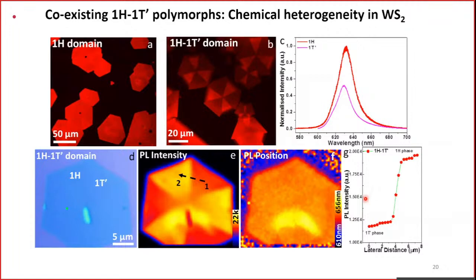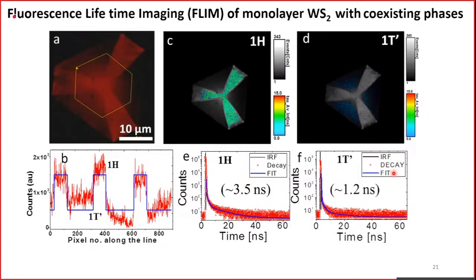And again, when we looked at the PL profile, we can see, going from one phase to another phase, there's a huge jump in the PL intensity. Not only the PL intensity, we also looked at the lifetime, because intensity is an extrinsic parameter. It can vary due to many reasons. Whereas the fluorescence lifetime is something intrinsic to the semiconducting material, like quantum dots and so on. We looked at the lifetime imaging. Again, we see a contrast between the 1T prime and 1H phase. And there is a 3 times difference in the lifetime. 1H phase has around 3 nanoseconds, whereas 1T prime has 1 nanosecond of lifetime. Lifetime, I mean, when the light falls on your semiconducting 2D material, an exciton is created, right? An electron-hole pair is created. What is the actual typical lifetime of this exciton? That is what we are trying to capture.